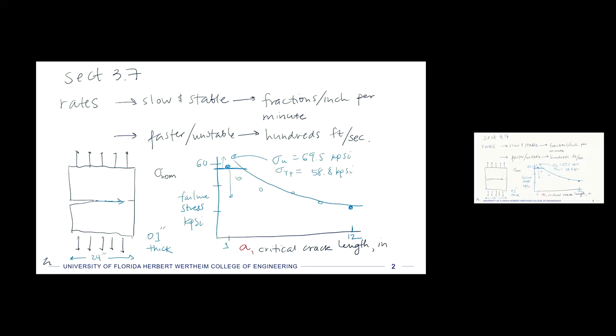So it's just something that does not hold any stress. And then this line that I've drawn on here, I'll highlight it in a different color right here, can be represented by a constant that incorporates both the stress and the crack length. So when that happens, we're going to call this the critical, I don't know, we could call it the toughness, right? Fracture toughness. And it's going to have a constant value. And it's going to have weird units. So it's 110, and then it's KSI times the square root of inches, okay? So we'll see where that comes from in a few minutes.